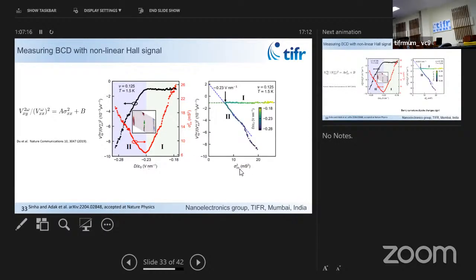And so our key innovation was that this scaling relation becomes complicated because of other kinds of scattering. So people mostly do this kind of experiment with temperature, and that makes analysis complicated. We did this at a fixed temperature by just varying the electric field. And if you do a parametric plot, essentially remove the electric field and combine these two, you will see a plot which comes out like this. And if you do the scaling analysis here, you see the intercept up to this point is 1, and then as you go past this point, it radically changes, in fact flips sign.